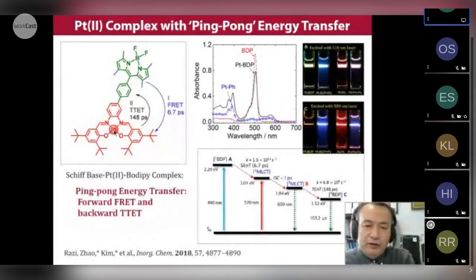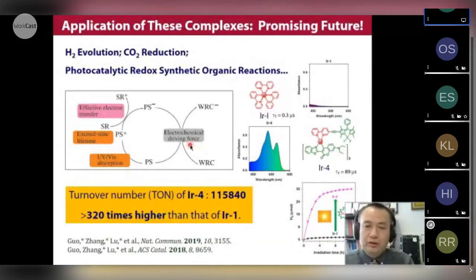Then we will have a fast intersystem crossing that takes less than 1 picosecond. Then we observe a backward triplet energy transfer to the BODIPY part. It takes about 150 picoseconds. In this case, we are unable to observe the singlet state because the intersystem crossing is faster than the singlet energy transfer. We don't get an accumulation of singlet state in the solution. So we always observe the singlet energy transfer and then the triplet energy transfer backward to the organic chromophore.